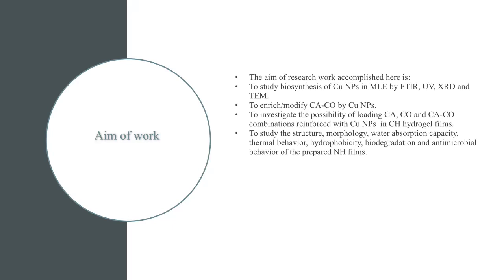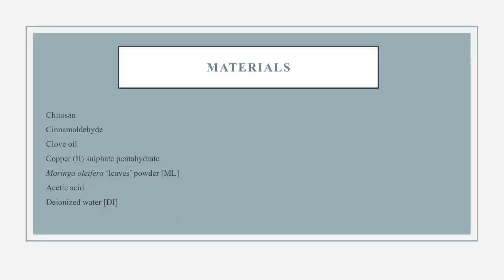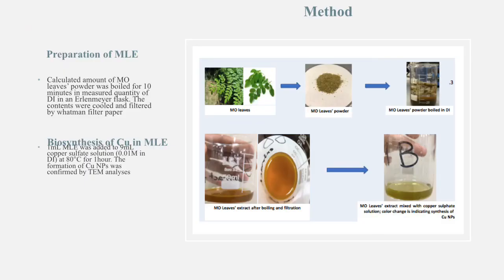To study the structure, morphology, water absorption capacity, thermal behavior, hydrophobicity, biodegradation, and antimicrobial behavior of the prepared nanocomposite film. Materials: chitosan, cinnamaldehyde, clove oil, copper sulfate, Moringa oleifera leaves powder, acetic acid, deionized water to prepare hydrogel. Our method began with the preparation of Moringa oleifera leaves extract.